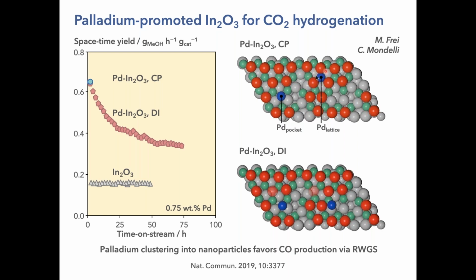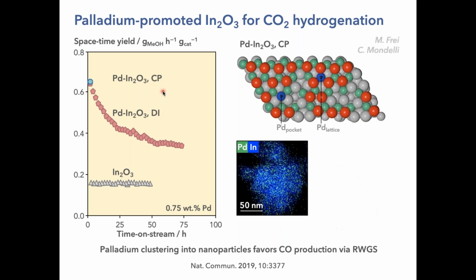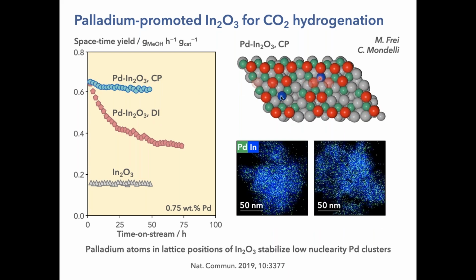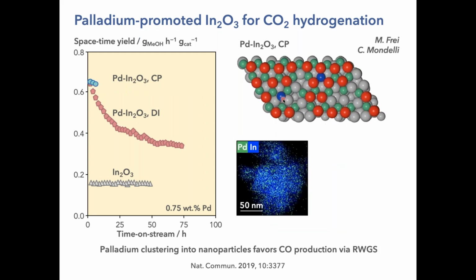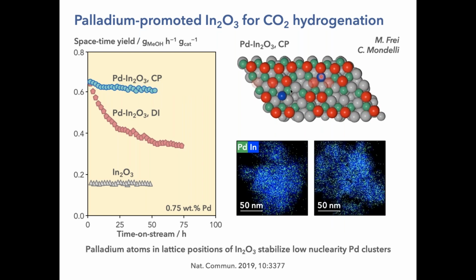But actually, this palladium lattice species has a very important role in the design of the catalyst. So that palladium pocket is the same as this palladium pocket. This is surface palladium site. Again, we have a very high initial activity, very similar to the dry impregnation, but the difference is that this catalyst is stable. This species is mobile, but this species is not. So what happens, and this is our assumption of looking no change in atomic dispersion, is that this atom should move actually, exactly, there you go. It's actually anchored to this site, forming a dimer.